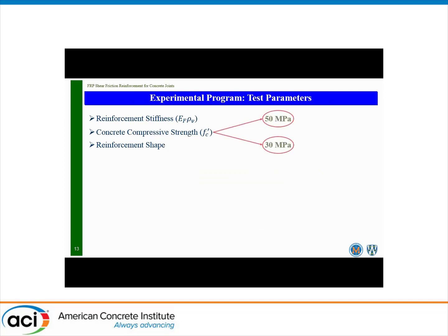The testing parameters included reinforcement stiffness, which contains two values: the Young's modulus of the GFRP reinforcement used, and the reinforcement ratio, defined as the ratio between the cross-sectional area of the GFRP over the contact area of the concrete.